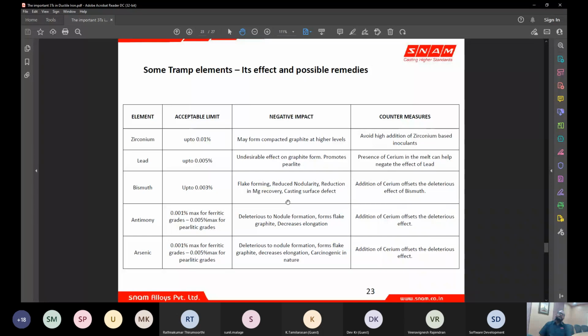When zirconium crosses beyond a limit, it starts providing compacted graphite iron. That means it changes the morphology of the graphite at the same levels of residual magnesium and sulfur. So with the same sulfur and same magnesium level, an increase in zirconium can lead to vermicular graphite. That means you should not add more zirconium inoculant, and any other source of zirconium coming up should be avoided.